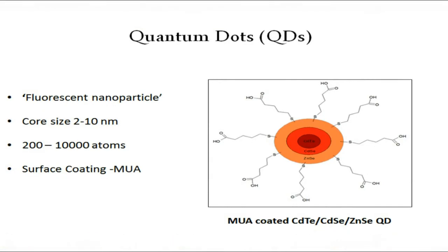For those of you who are new to quantum dots, quantum dots are fluorescent semiconductor nanocrystals in the size range of 2 to 10 nanometers with unique photophysical properties that enable a host of biomedical applications in medical and surgical oncology. Their unique photophysical properties include a broad excitation spectra, a narrow symmetric emission spectra, and high quantum yields as well as high photostability.